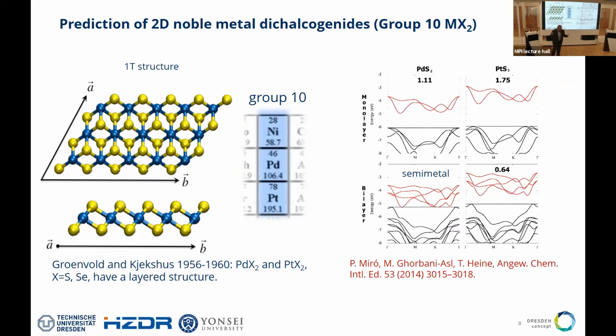So you look into these materials and they are metallic as a bulk. You do a calculation of a monolayer and they get semiconducting. Okay, well, interesting. So we looked into that a little bit more carefully. Palladium disulfide, platinum disulfide, they are semiconducting. If you go to bilayer, one of them shrinks in the band gap very significantly, the other one gets metallic. I think that's pretty fantastic.